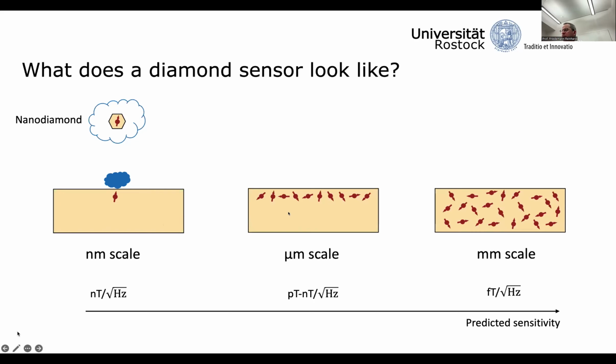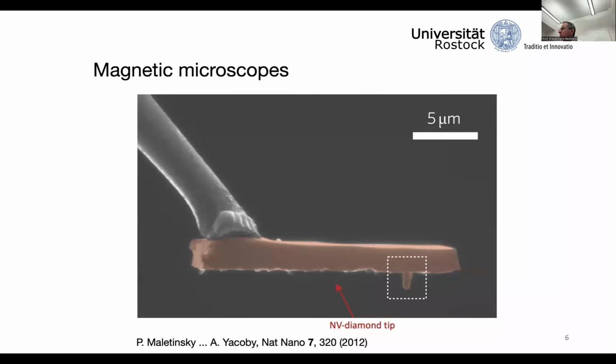And theory predicts that by doing this at the micrometer scale, we can essentially go down to the picotesla per root hertz scale, and doing this on a millimeter-sized, large diamond full of NV defects, we could even go to the femtotesla per root hertz scale. Many experiments have been performed. For example, this dream that I sketched a few slides earlier has become reality.